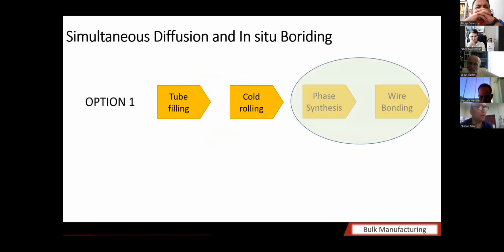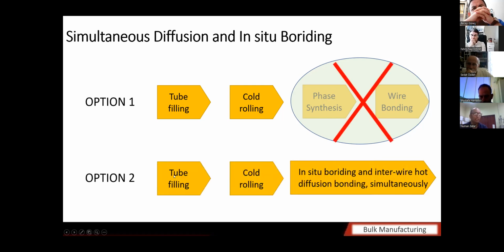It is not as simple as that, because after the phase synthesis, the sheaths of the wires are going to be oxidized, and you will have to clean them, go through a lot of machining, chemical cleaning, maybe physically abrading them before you can bond them together, which is not practical. So we use the second option. This is inevitable. You cannot escape from these two steps, because you have to have composite wires at 1 millimeter, 1.5 millimeter level. So we want in situ boriding in the cores of the wires and interwire hot diffusion bonding at the sheaths of the wires at the same time. Only then it is going to be something practical.